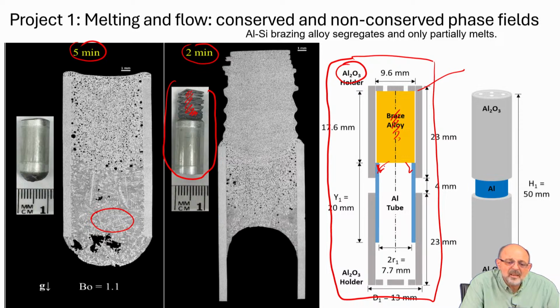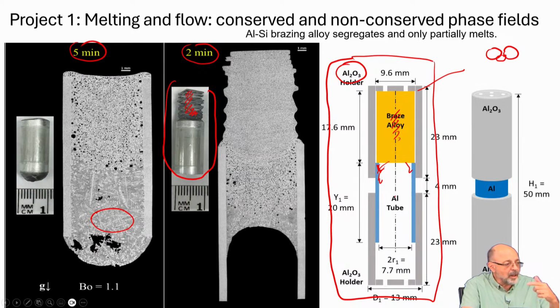So what happens here is that the liquid is pulled out and away towards the bottom, and what remains on the top is some sort of granular material which looks something like this. These are aluminum grains, and the gas comes from that additional compound. Chemical reaction with the oxide produces a gas, or it could be nitrogen.